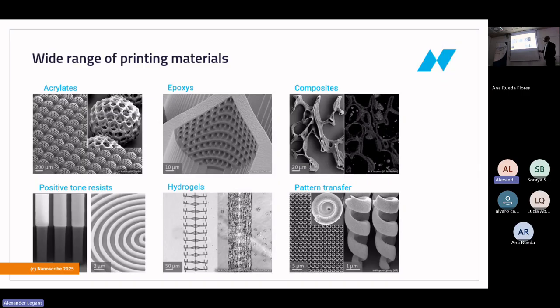Positive tone resist means, before I showed you, you start with a monomer which you expose to get a polymer. Here for the positive tone resist, it's the other way around. You have a polymer. With the laser, you break up the bindings. Then later in the washing bath, you wash out the monomers. That means more or less you create these types of gaps or edges in between.